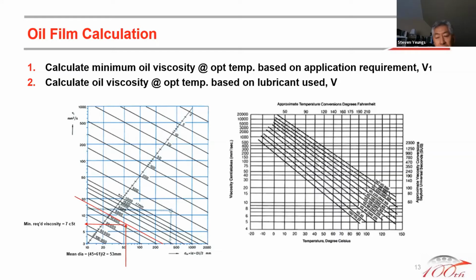So I made use of another graph, looking at 55 degrees centigrade at 7 centistokes. You can see I actually need something really thin to be satisfied with the oil film conditions. But let's look at what they're using, a 46 weight. Based on that, at 53, at that point it's about 25 centistokes. So when I do the calculation of the viscosity ratio, I get about 25 over 7, which is 3.5.